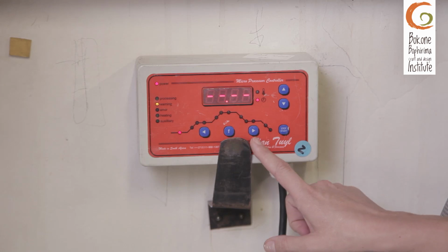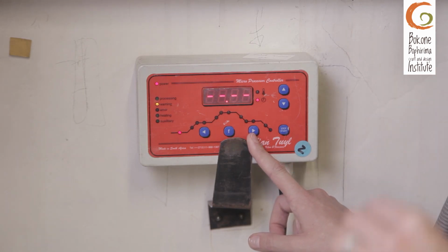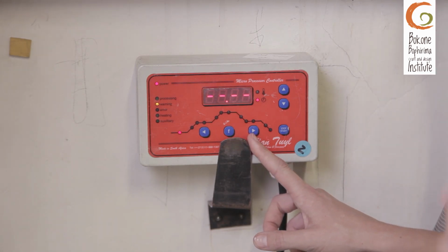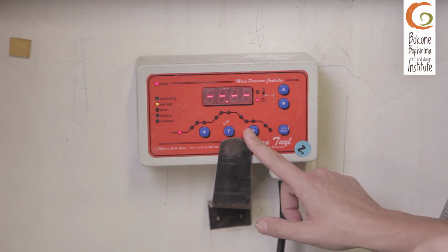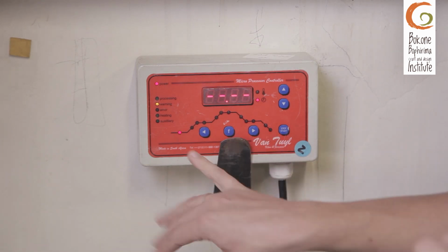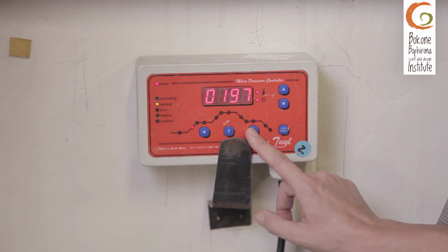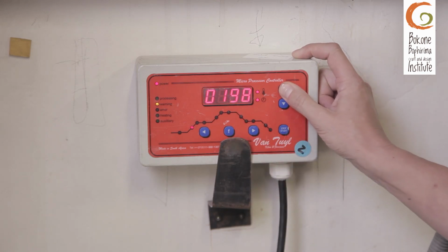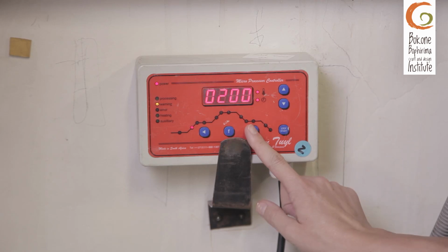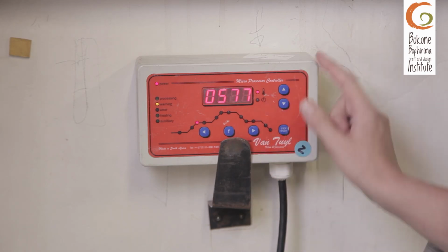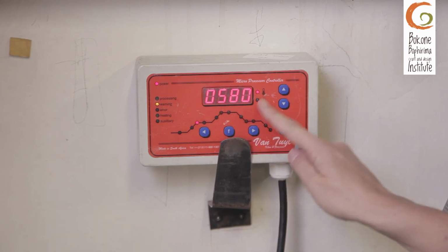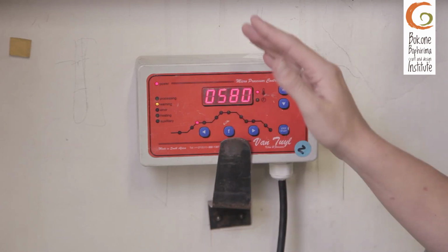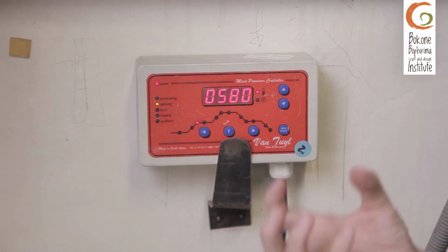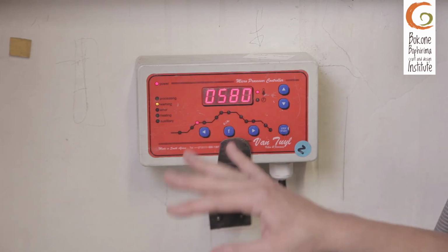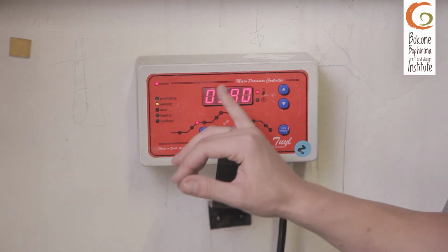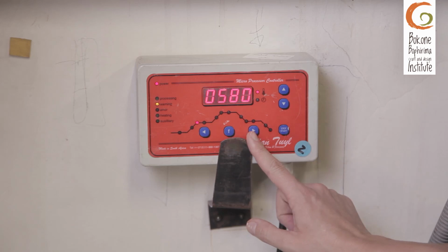All right. And remember, the thinner your glass is, the longer you're going to have to hold it at the top temperature, because it does not have gravity behind it. We're not going to delay it. We're going to start the process immediately, and we're going to take it up 200 degrees an hour, so still quite slow in glass, up to 580. Once again, 580 is our point. Anything below 580, our glass is fragile, so we need to make sure that we are quite delicate with our glass in this process.